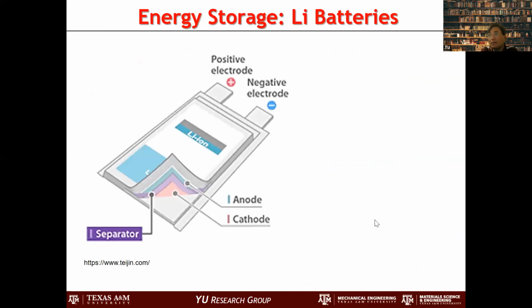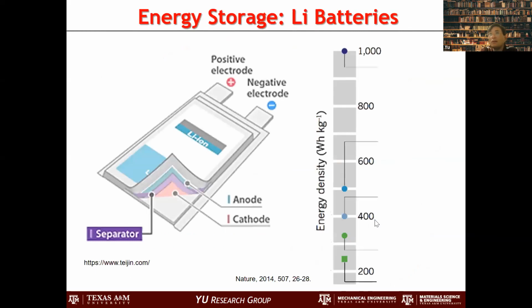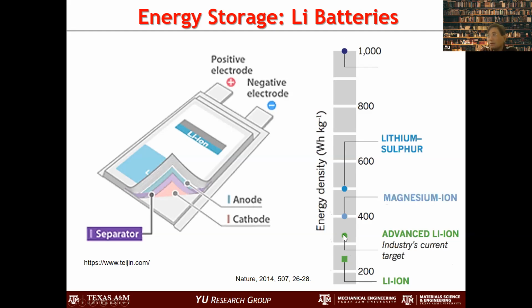Now, in that sense, people want to develop high energy density batteries plus low cost batteries. Currently, this is lithium ion here, which is really at the bottom. This is what industry wants to achieve, but it's still not quite there yet. And this is the magnesium ion. This is lithium sulfur, which is actually quite large compared to that. So if successful, on top of that, the sulfur is really low cost. Sulfur is not much used, but whenever you produce oil, you basically generate sulfur. You want to take sulfur out, so it has not much usage. So sulfur is very low cost.